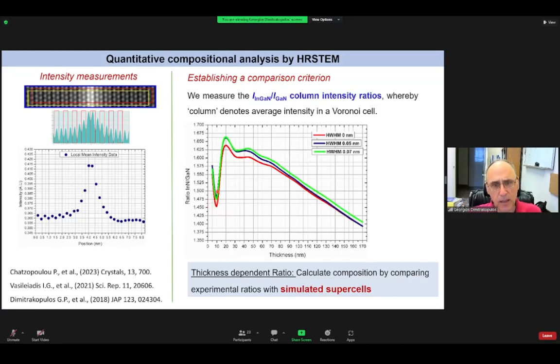So this is a pure binary in this simulation. You see that for very small thicknesses of the TEM foil, there are very large variations. And then if you go beyond, let us say, 40 nanometers thickness, then we have a linear relation that we can trust. And of course, there are also variations due to the source size. So simulation is a must if you want to be quantitative. Image simulation based on proper structural models.